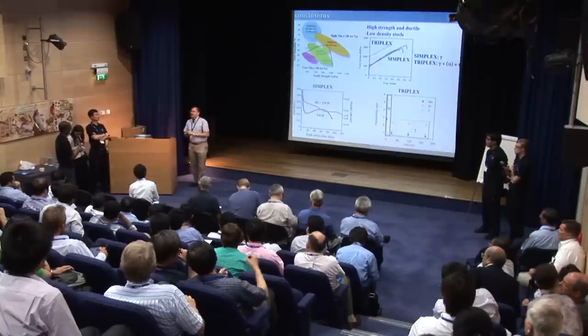And are you sure that kappa is cubic? I'm sure. Yeah, this is a good question. Sure and not. According to the diffraction patterns, conventional TEM, you can nicely see that it's an ordered L12 type, and it's quite simple because you see extra spots. But what we are currently interested in doing is characterizing the lattice parameter along the two directions, to see whether this is really cubic or not. This is still ongoing, but according to the literature, this has never been done. It has only been analyzed by XRD, for instance, always assuming an L12 type of structure. So the real structure is probably different.